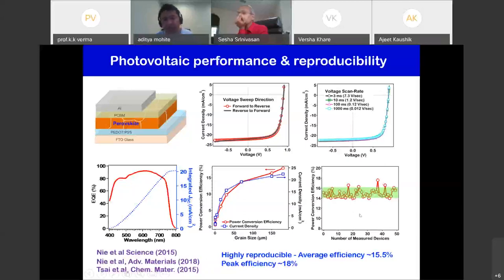What's really important when you're doing these types of measurements is statistics. Really this 18%, if you see on this plot, is just an outlier. And so this is not really a great number to report. What we reported was an average efficiency of 15.5%. Anyway, so this was great.